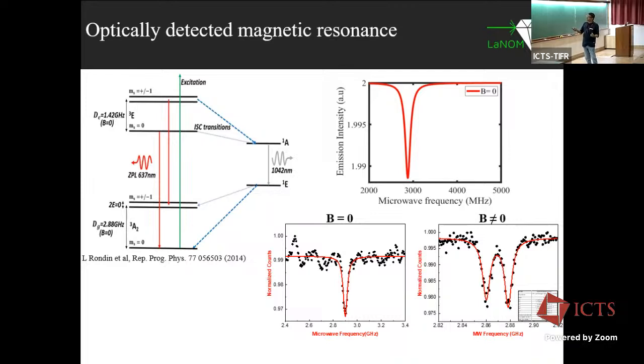And when you apply a magnetic field, you can see the Zeeman splitting. The peak is separated into two, because now the degeneracy of these levels is lifted. So we developed this also. We struggled a little more here than with the Hanbury Brown and Twiss experiments. But I was so happy to show you that we got it in our lab.